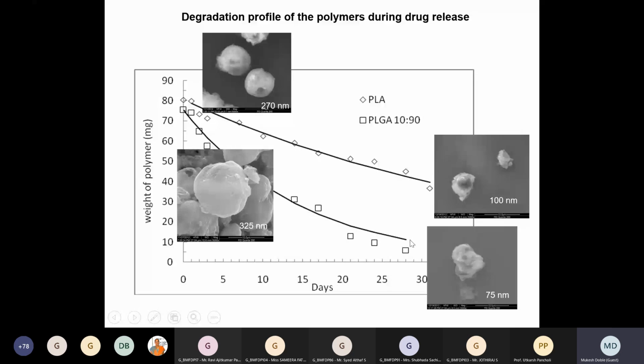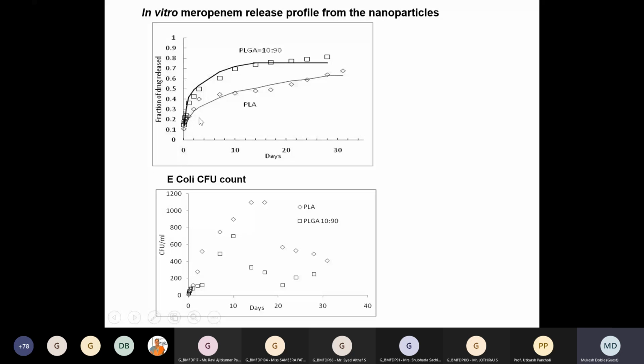You can see the particles also becoming smaller and smaller, from 270 nanometers going down to 100 nanometers here, and here from 325 to almost 75 nanometers. When the polymer slowly biodegrades, the drug also gets released as a function of time over 30 days. PLA is not able to release as much drug. PLGA is able to release most of the drug, whereas almost 20-25% of the drug is still retained in PLA. So that's another advantage of this polymer. It's able to release as much drug as possible. It's also degraded much more than PLA, and so the released drug is able to kill the bacteria.